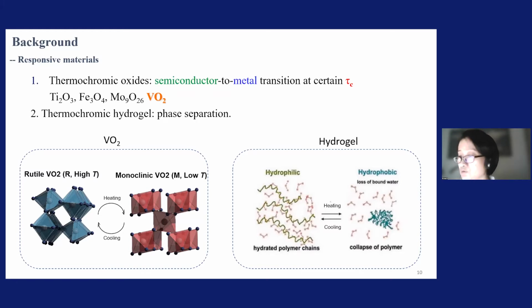Being very close to room temperature means it will be very readily used for many applications, because a device is about change, right? You give it an input, the output has to be different, right? So if something is close to room temperature, that makes VO2 a very much wanted and loved material in the research community, not only in thermochromic oxide. VO2 requires a near room temperature phase transition from semiconductor to metal, changing from rutile phase to monoclinic phase. Rutile is the high temperature, metallic phase, and monoclinic is the room temperature phase, a semiconductor. Simply by changing the temperature, and remember, it is only 68 degrees. It's a wonderful material.